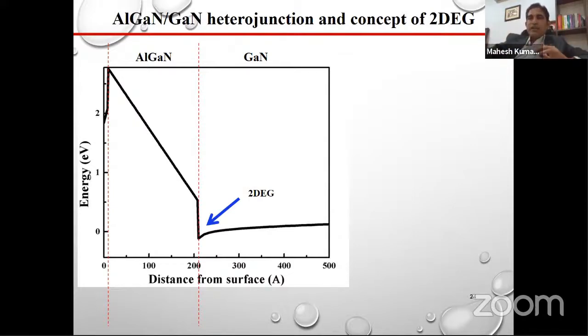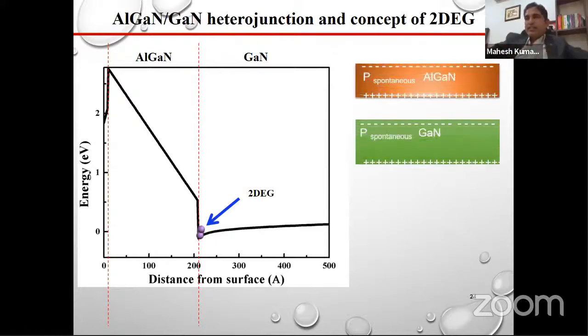Now in the conduction band, these electrons will be trapped at the heterojunction. So we have gallium nitride, we have aluminum gallium nitride, and here we have basically a valley at this junction. Because of this polarization, or you can say because of this electric field, these carriers will be trapped at the heterojunction. So in this material at the junction, we have a free electron gas, basically a 2D free electron gas. In the third direction, we can take the contact and make these high electron mobility transistors.